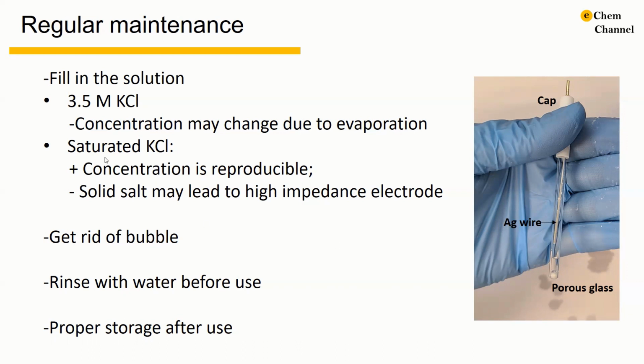We can also use the saturated potassium chloride. The good point is that the concentration is reproducible and even temperature independent. The problem is that the solid salts that emerge in the electrolyte may lead to high impedance. Before use, we need to get rid of the bubble by gently knocking on the electrode. Then we rinse the electrode with water.